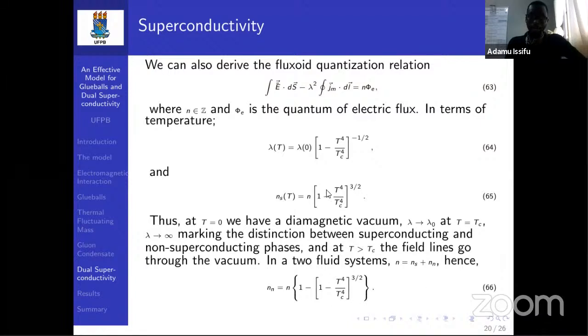So using this as a guide, we can express this expression. Now here we can analyze this equation, the monopole number density. We realize that at T equal to 0, that is when the superconducting material is cooled down to T equal to 0, you have all the electrons conducting in the system being the total number of the monopoles in our case, the total number of conducting monopoles in the system. And then as the temperature increases, this superconducting monopole density keeps decreasing.